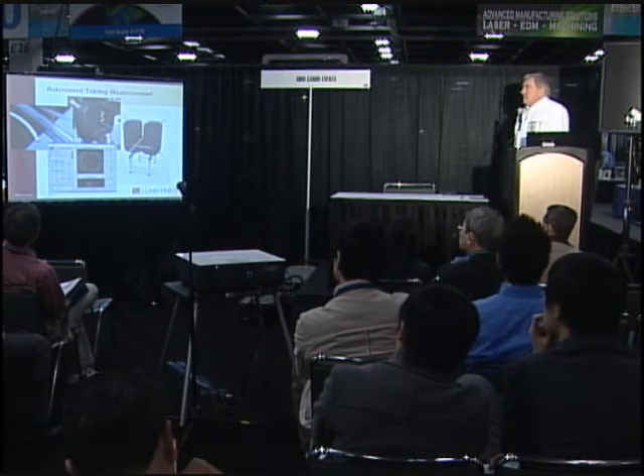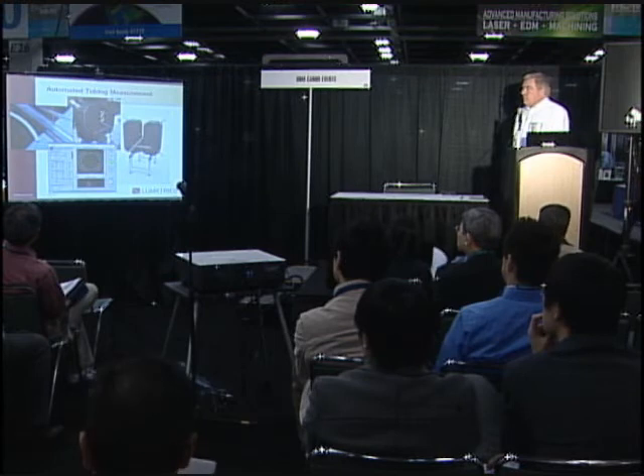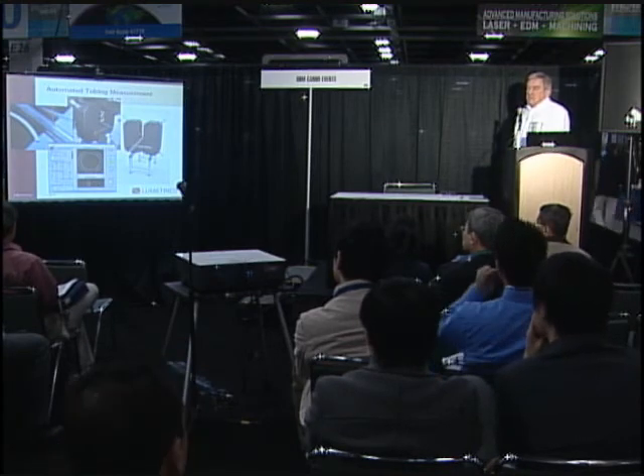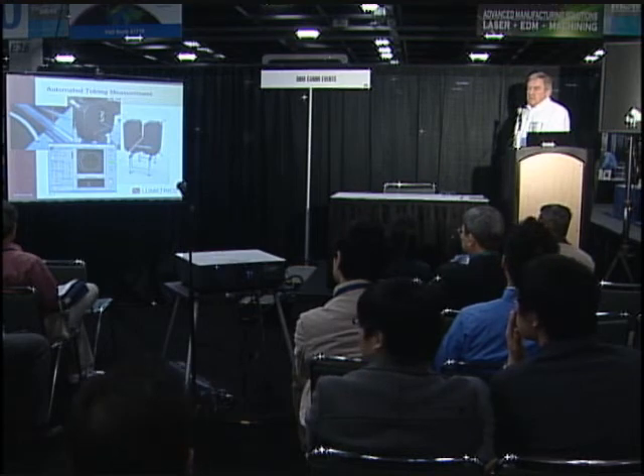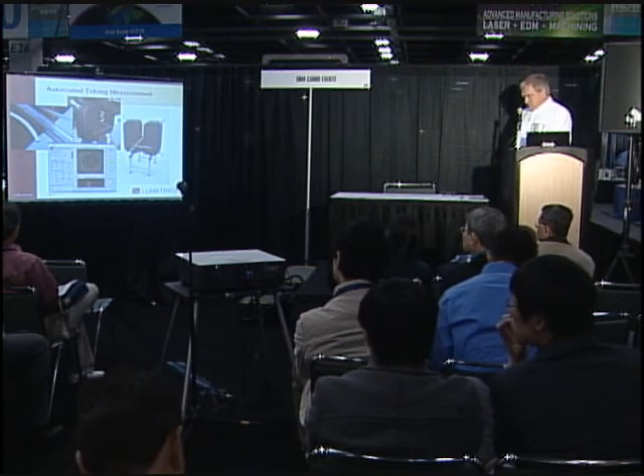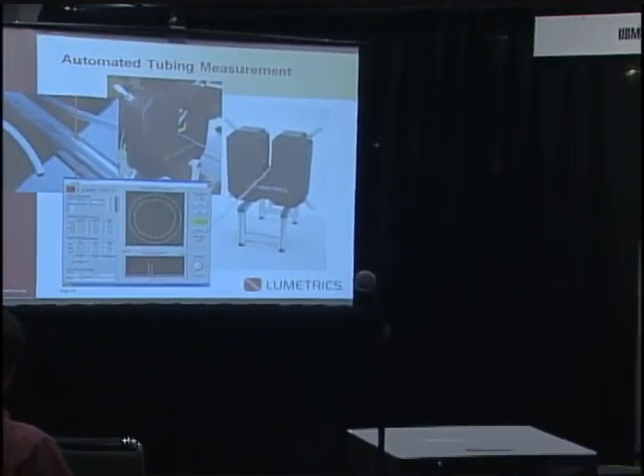We've done quite a bit of online work, both in flat film, multiple webs, and also tube, and we have a system in operation at our booth. We have installations for food packaging, for example, where we measure eight webs on a food processing line, measuring the inside barrier layer of each web, doing closed-loop control to control the die bolts that make the middle layer thicker or thinner. In that installation, there's a $7 per pound polymer in that middle layer, so they need to tightly control thickness to specification. We're using four probes so you can collect lots of data as your extrusion is moving. We've tested speeds on flat lines up to 1,500 feet per minute — so you collect lots of data even on moving webs.